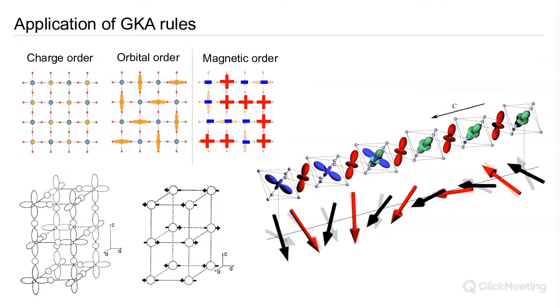And we can also understand why we get one-dimensional behavior in potassium copper fluoride, because what we essentially have is the case that we have a singly occupied orbital facing a singly occupied orbital along the c-axis, making chains. So we have strong antiferromagnetic exchange interactions along these c-axis chains. But then we have a magnetic orbital facing a non-magnetic orbital within the plane, giving rise to essentially negligible exchange interaction in that direction. So far so good. The GKA rules tend to work pretty well.